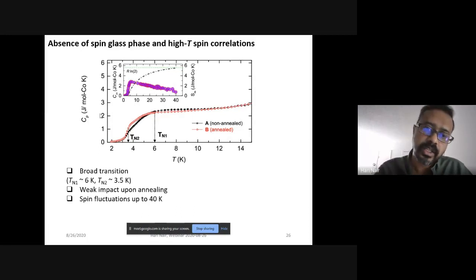And the two curves, black and red, on the main panel just show that we measured two different samples. One is annealed and one is non-annealed. The reason why we did that is to check if by annealing we can remove the defects. We saw broadening of X-ray peaks, and that is the defect that I'm referring to here.